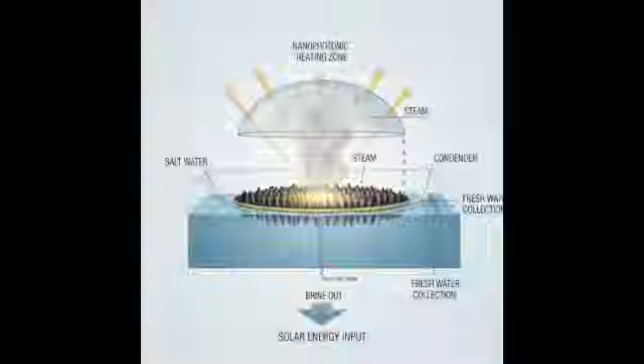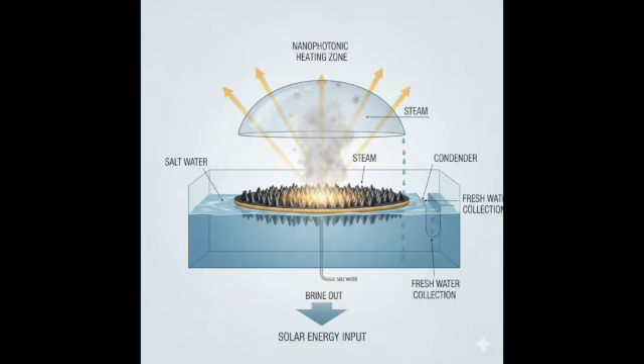You're no longer relying on heat conducted from the bulk. That sounds incredibly efficient. You avoid heating the entire bulk feed, minimize heat loss during transfer, and you directly combat TP. This allows PMD systems to operate much more effectively, achieving higher flux and better thermal efficiency. Plus, I read something about lower operating temperatures being beneficial. Yes, that's another significant advantage.